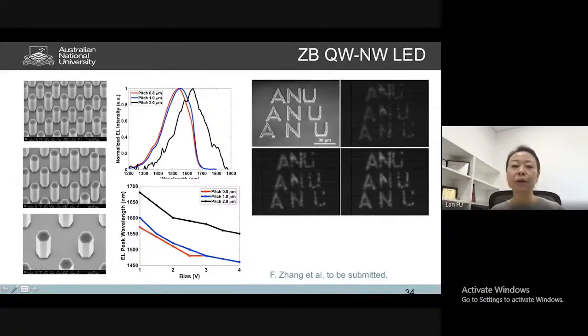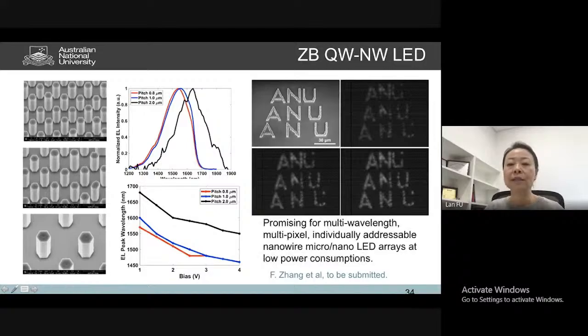And of course, if we design the nanowire array into a very small area, you can see each line has just a few nanowires. We're still able to get them emitting quite nicely. So this is our ANU, Australian National University logo, made from the LED. So we think this is very promising for multi-wavelength, multi-pixel, individually addressable nanowire LED arrays at a very low power consumption in the future.